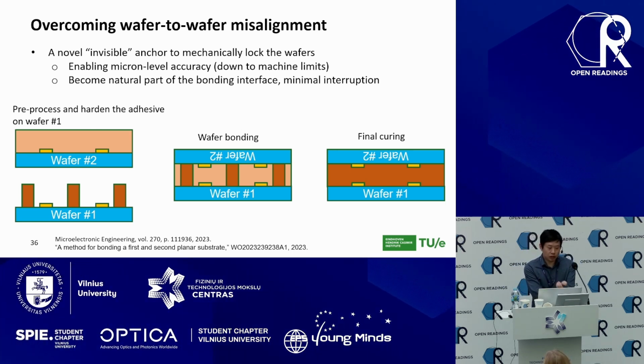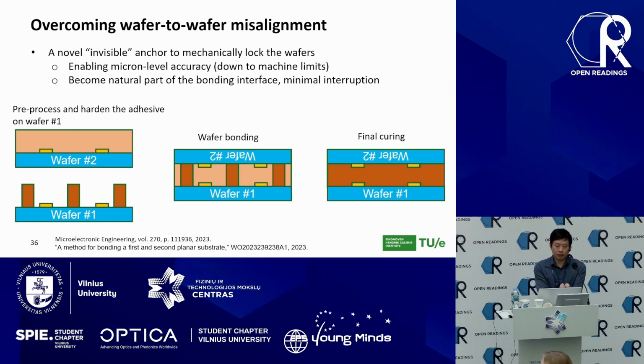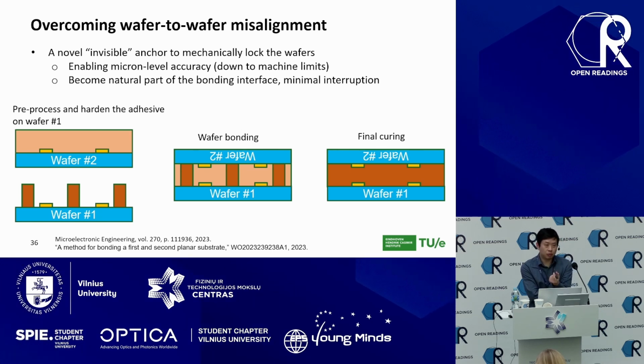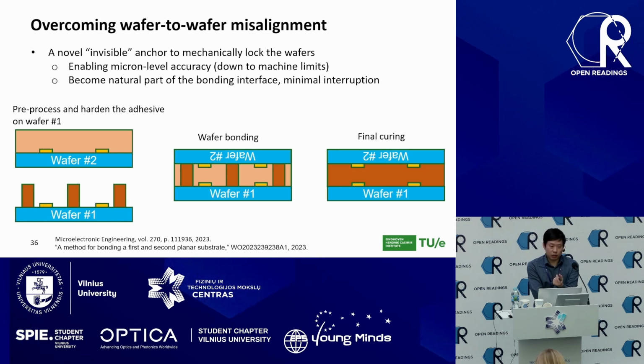We first, as you can see, prepare the two wafers. One can be photonics, one can be electronics. And on one of the wafers, we not only coat the polymer, but we actually pattern the polymer and cure it. So as you see on the bottom one, on wafer one, it's a cured, hardened polymer, which is actually very stable. On the other wafer, we don't do it. It's still a liquid phase polymer coated on the wafer.